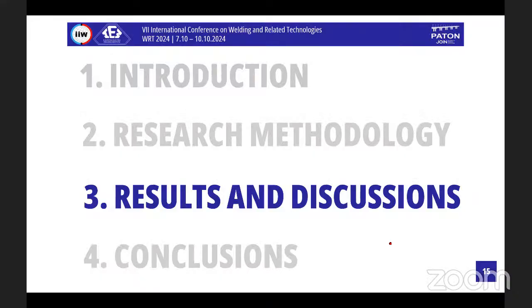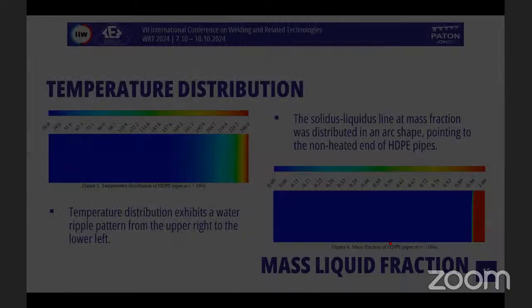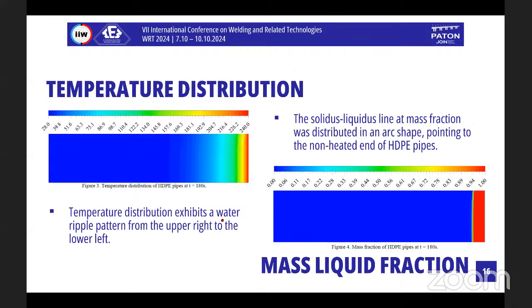Part three: some results and discussions. There are two pictures about the temperature distribution and the mass liquid fraction. As we can see, the temperature distribution exhibits a water ripple pattern from the upper right to the lower left, like this. And about the mass liquid fraction, the solidus and liquidus lines were distributed in an arc shape pointing to the non-heated end of the high-density PE pipes. It's like this.